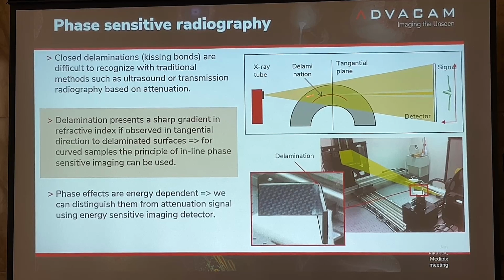The delaminations were also discussed here. Exactly the same principle I was showing for this edge enhancement can be used for that. We see delaminations only when we can access the lamination in this tangential direction, so for flat samples it is difficult to do that. But luckily there are some structures which are of this L shape. This is something from the aerospace industry, and if we vibrate it, here in this bended part, you start to have delaminated layers.